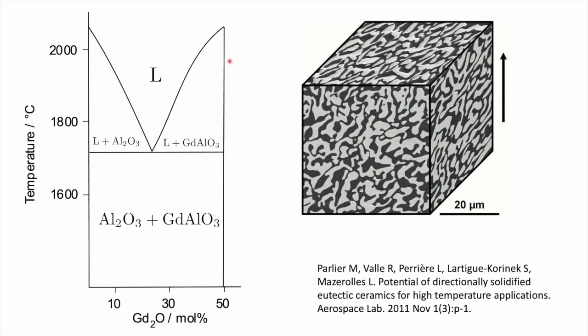Notice that there's no two-phase field on this side, or a very, very thin two-phase field on both sides, because the solubility of gadolinium oxide in alumina is more or less zero, and similarly the solubility of alumina in gadolinium oxide is more or less zero. Okay, so unlike the lead tin diagram, there is no mutual solubility of alumina and gadolinium oxide in each other. And here we have the liquid plus alumina phase field and the liquid plus gadolinium aluminium oxide phase field. And here is our eutectic composition and eutectic temperature.